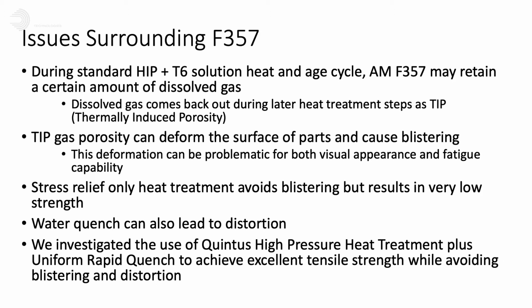Right, so you see hot isostatic pressing as a way of combating this? I think hot isostatic pressing is certainly a way to combat this, but it also gives us some unique opportunities with what Quintus is doing to combine HIP and solution to limit the thermal exposure the part is going to see at lower pressure to just the aging process, which occurs at lower temperatures. And that should provide us a benefit to avoid the blistering.